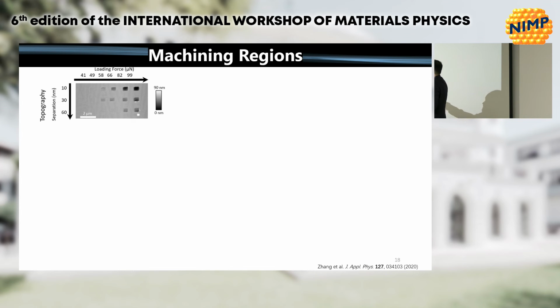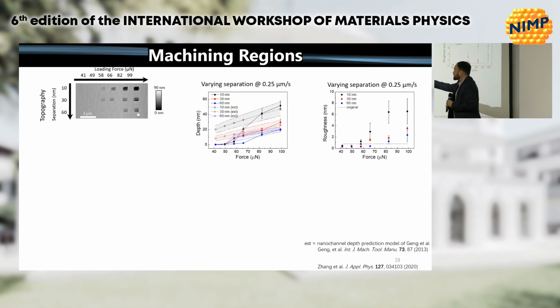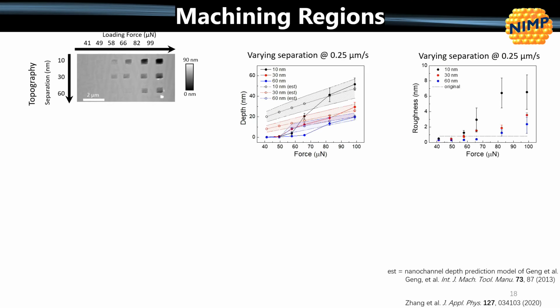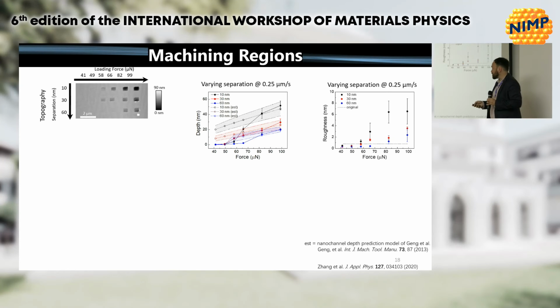But we studied it as a function of loading force and separation, so you can do a full AFM scan, or you could have a scan where the lines are separated by a certain distance. You can see, clearly you're removing more material the higher the force, and it's getting a little bit worse if the separation is increasing. We can plot this depth as a function of force, and roughness as a function of force, where roughness is a proxy for the quality of the removal of the material.